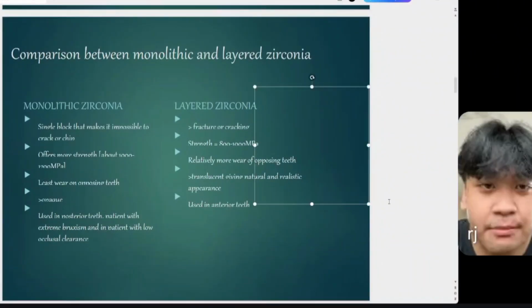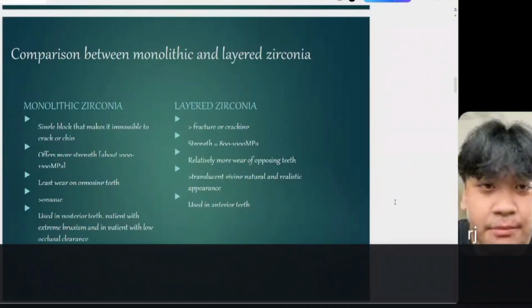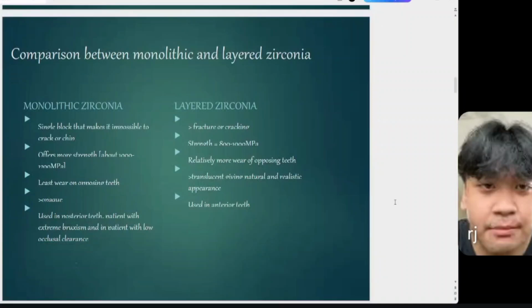The monolithic zirconia, again, is a single block that makes it resistant to cracking or chipping, while the layered zirconia is a bit prone to fracture or cracking because it is fabricated by applying ceramic powders to it. So the porcelain veneer is a bit prone to chipping and fracture. Next, the monolithic zirconia offers more strength, about 1,000 to 1,200 megapascals, while the strength of the layered zirconia is around 800 to 1,000 megapascals. The monolithic zirconia causes the least wear on opposing teeth, while the layered zirconia causes relatively more wear on opposing teeth.